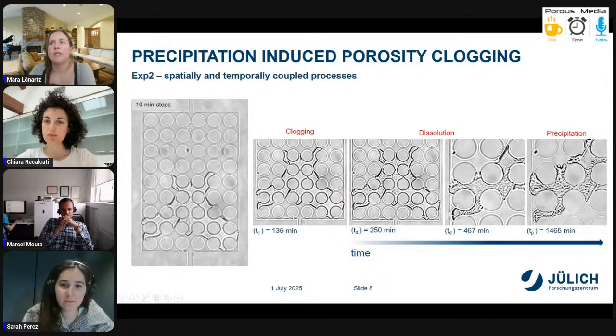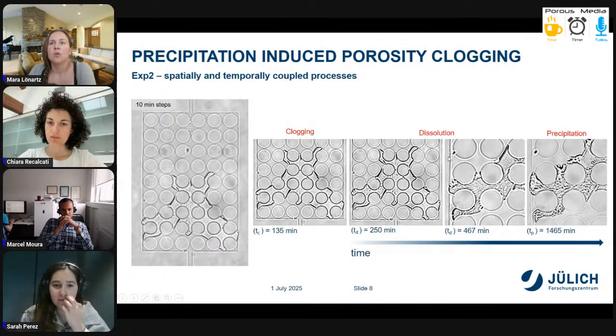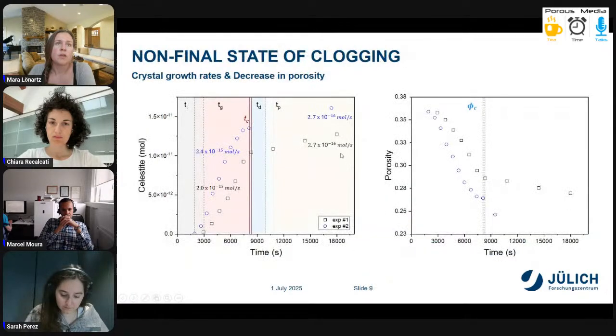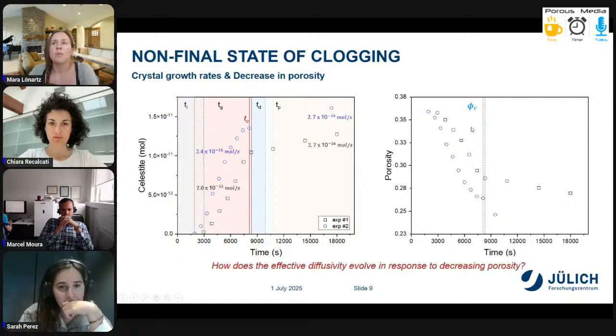and reprecipitation reactions. So just from the images, I could derive the crystal growth rates, and we could see that, due to the post-clogging reactions and further precipitation, the clogging had an impact on the precipitation rate. So it was lowering it down, and we could, of course, measure the critical porosity.